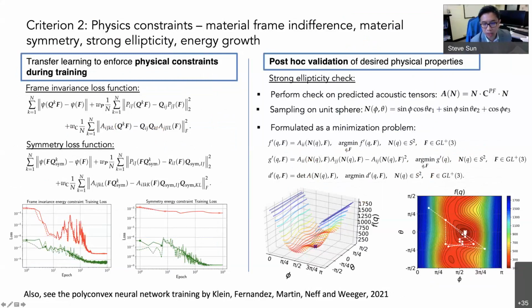Another thing that we can also do is to check the acoustic tensor behavior. So when we compute the tangents, for a given orientation n, we obtain the acoustic tensor, and then the eigenvalue of the acoustic tensor gives us the wave speed of the material. In this particular case, we can find out what the minimum of the wave speed is, and we can ensure that the constitutive law leads to a stable result by ensuring that the wave speed is not going negative.